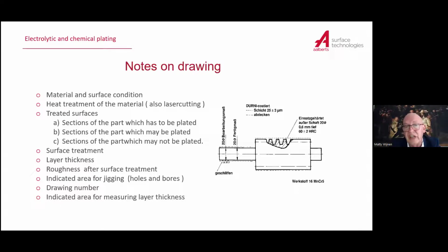Then on the drawing, it's important which section has to be plated, so where the functional part of the coating is, which section may be plated, and which section may not be plated or is not allowed to be plated. And please keep that part not to be plated as small as possible, because that is the part which you have to mask, and there are a lot of methods to do that. There are holes where you can use stops, you can tape, you can use lacquer. There are a lot of things to mask and to cover your parts. The problem, however, is that the bigger the part is that you don't plate, the more difficult it becomes. And I have a nice example for that, and that's part 9, Arno. And then show that, please.